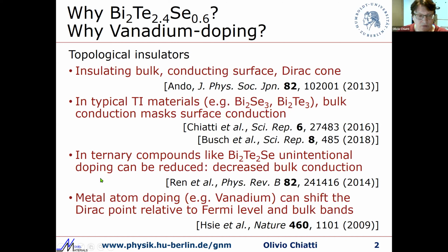In addition, if we use metal atom doping like vanadium, we can shift the Dirac point relative to the Fermi level and the bulk bands. And if these atoms are magnetic, we can also break the time reversal symmetry and induce a gap in the otherwise linear dispersion of the Dirac cone.